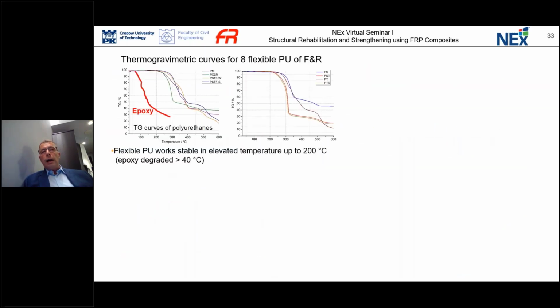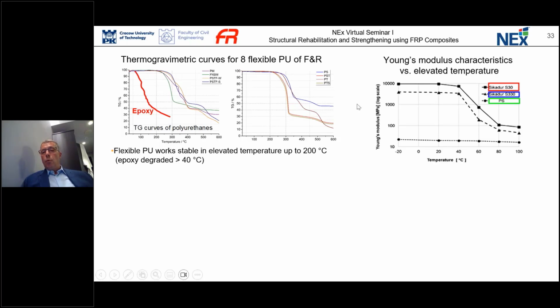So I would like to add some features of the polyurethanes. I'm talking about a group of polyurethanes that we use, and in thermogravimetric measurements, they showed that they have stable properties up to 200 Celsius degrees. So in working at elevated temperatures, the polyurethanes manifest very stable behavior. On the opposite side, when we use the epoxy over 40 Celsius degrees, it starts to degrade, so it is losing its properties.